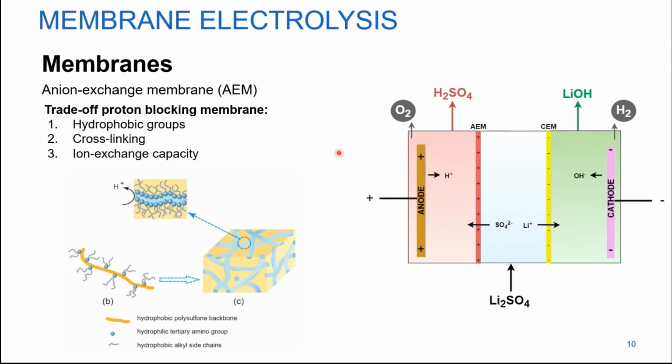then you will typically be looking at 3 specific characteristics in your membrane, all to block the protons from migrating back. So first of all, protons are surrounded by a lot of water. What researchers have seen is that a factor that influences the proton migration over the anion exchange membrane towards the cathode is the water content of your anion exchange membrane.